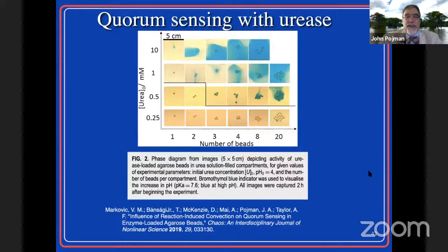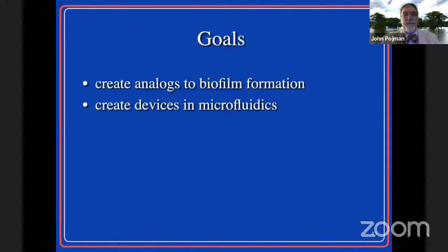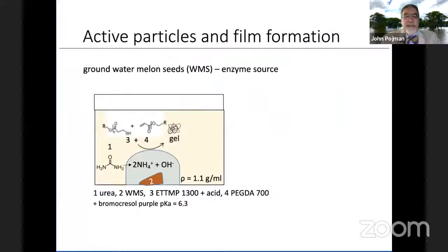And so this is just showing that if you have, say, just one particle, at this concentration it will never undergo this abrupt increase in pH. But under a certain situation here, if you go from 2 to 3, you can get the behavior. So they act together in a cooperative behavior, which is similar to how bacteria form biofilms. So we're right now trying to create analogs of biofilms and devices in microfluidics.